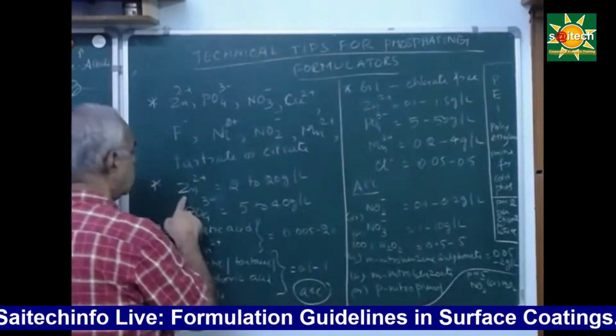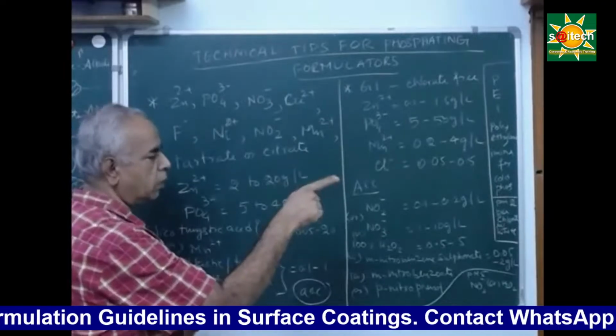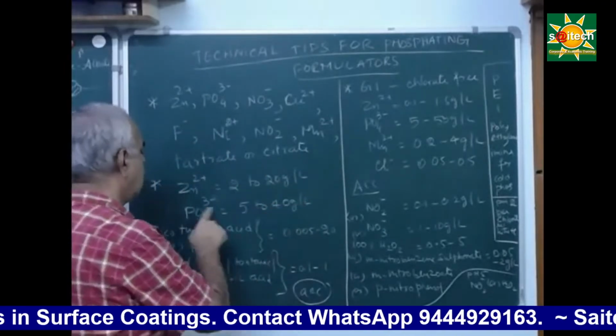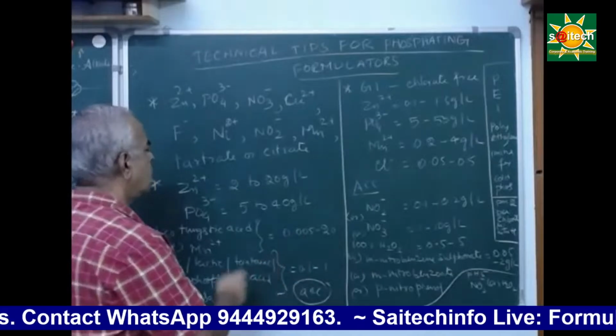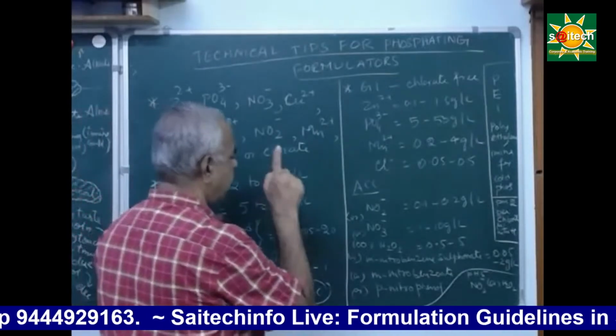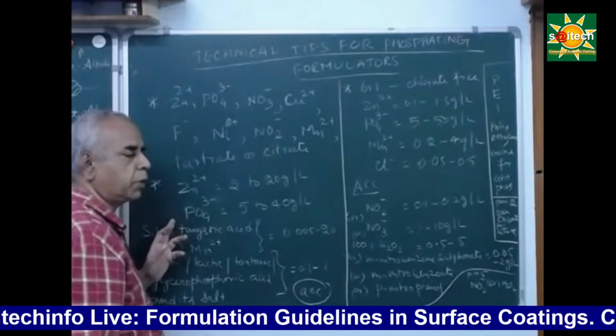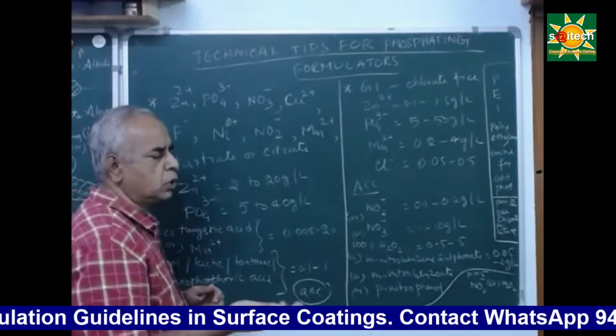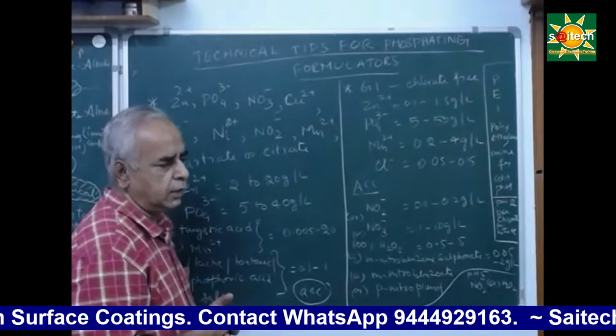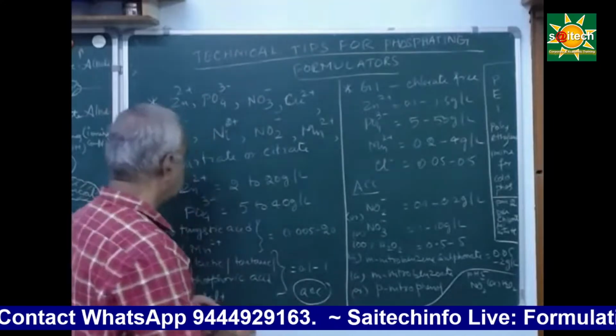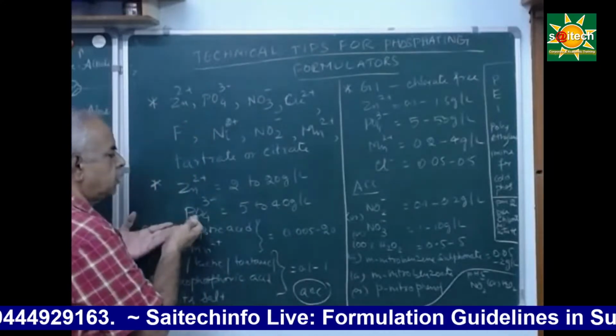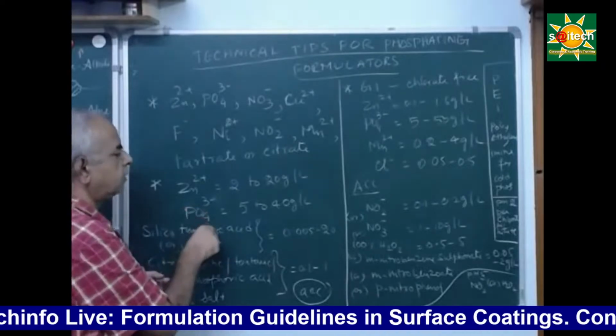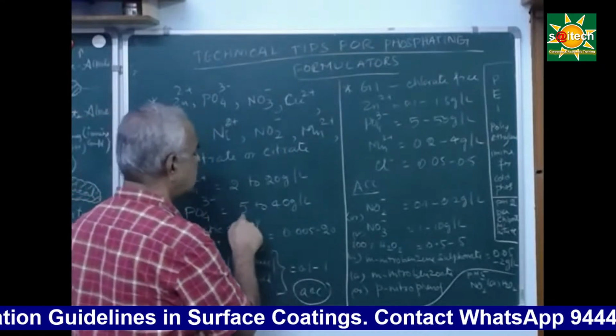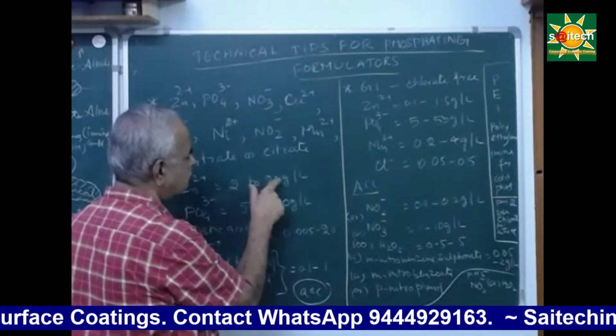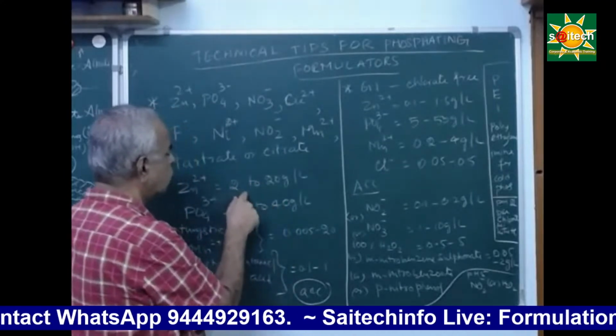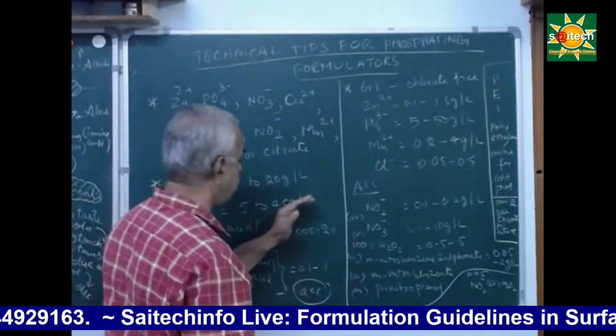Now, here zinc as zinc oxide. Remember, zinc as zinc oxide. The zinc oxide is a white powder, where the zinc content should be 2 to 20 grams. Clear? And phosphate means the amount of phosphate in terms of phosphoric acid, so it is given as H3PO4. The phosphate content should not exceed 40 grams, that is 5 to 40. So the same proportion should be maintained, almost a 1:2 proportion.